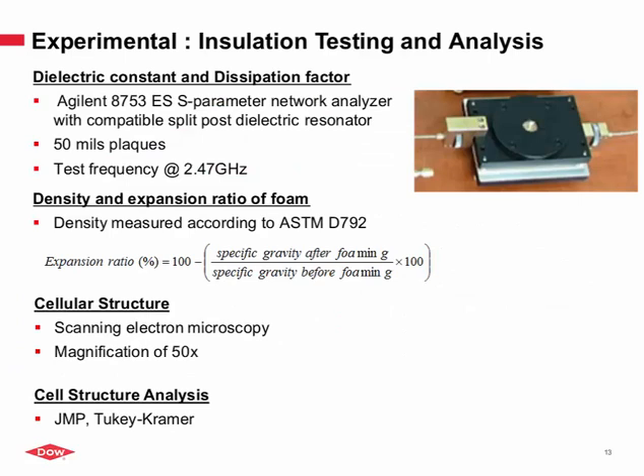For the electrical properties, we used an Agilent 8753ES analyzer on 50 mil plaques. These are solid plaques, so all data we are showing are on solid plaque. The frequency is 2.47 gigahertz, for the dissipation factor and the dielectric constant. The density is measured as standard according to ASTM D792, and then the expansion ratio is calculated using the specific gravity of the foam versus the unfoamed material. For the cell structure, we analyze the extruded foam using scanning electron microscopy, and of course we do image analysis on the electron microscope pictures themselves. That data is put into JMP, a statistical package, and we use a Tukey-Kramer type of model.